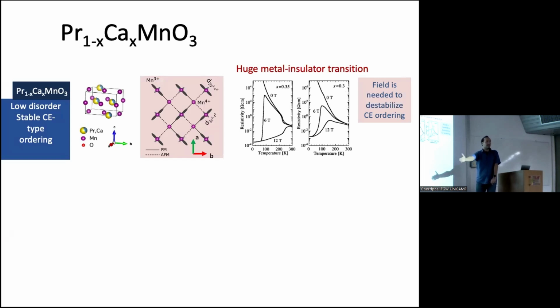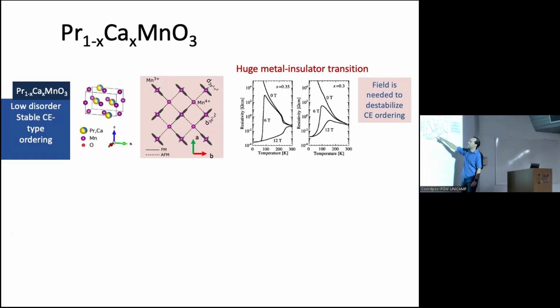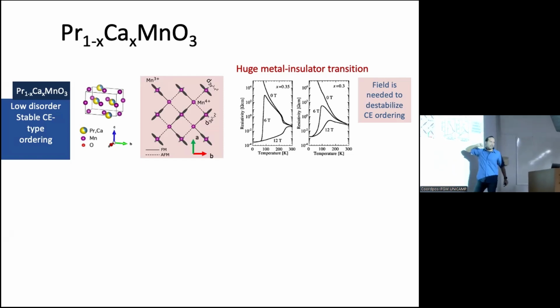by applying a field. Okay, because praseodymium is in principle a smaller radius than the lanthanum, so you can do that by field. If you apply a magnetic field, look at this. You have a huge magnetic field. You have a huge change in the resistance of the sample. You have a metal insulator transition.